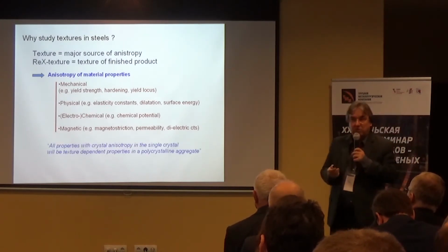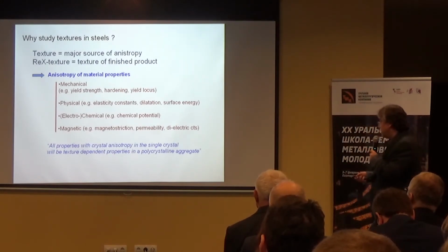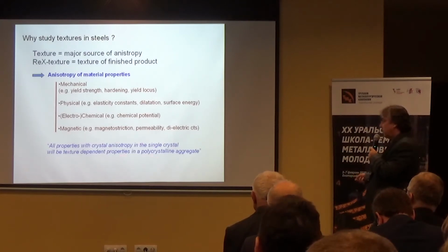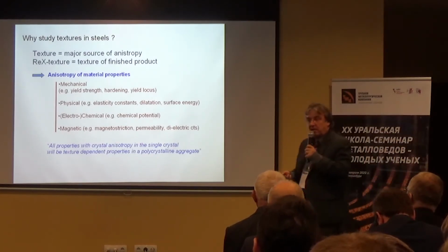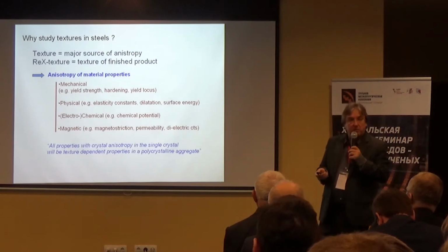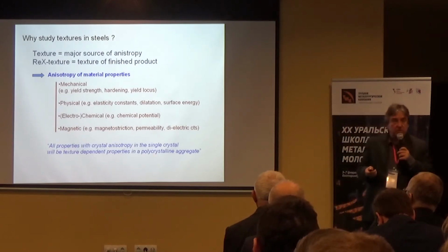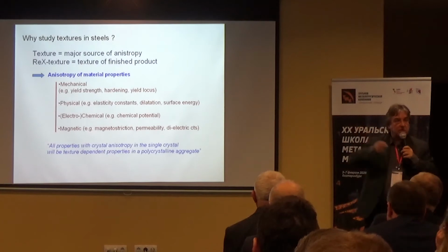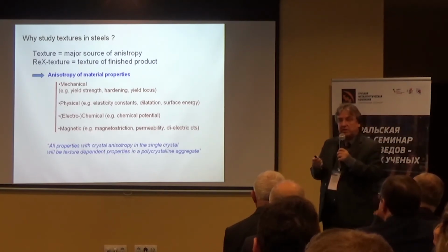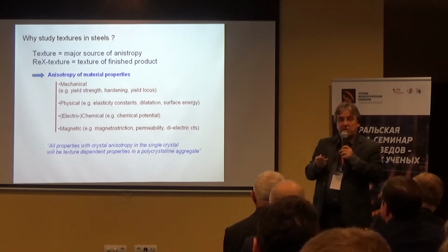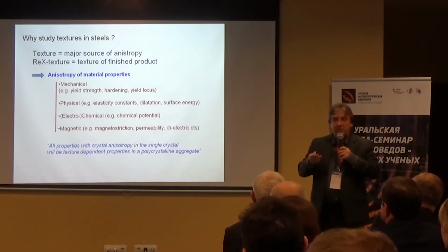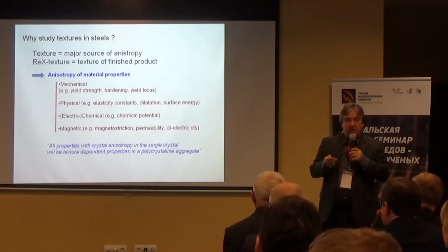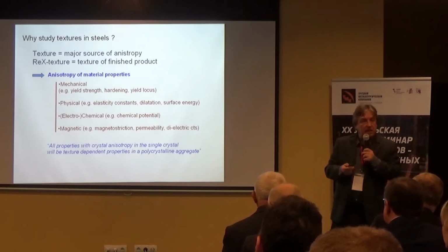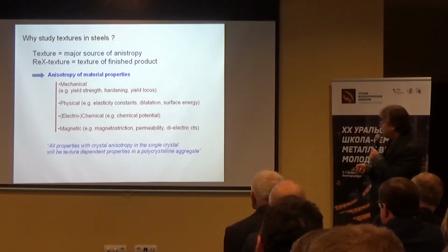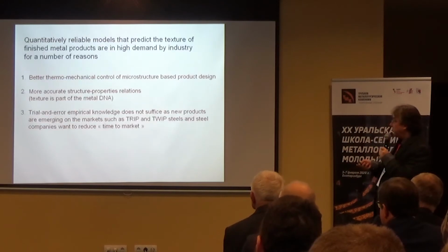In summary, you could say that all properties with crystal anisotropy in the single crystal will be texture dependent in the polycrystalline material. So if, for example, the elastic modulus is different in a cubic crystal in the 111 direction and the 100 direction, unless you have a textureless sample, it will introduce anisotropy in the macroscopic polycrystalline sample.